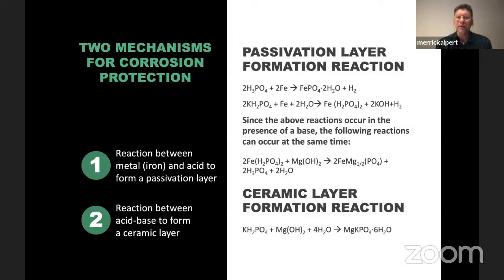And then second, what you're going to see as you're spraying it is the formation of that acid-base ceramic layer. Again, this is all going to look like you're spraying white paint. But if you slow down the reaction and think about what's happening, you are actually passivating the steel and you're forming an outer ceramic layer over the passivation layer. So again, Eoncoat is not a paint. It is a method for passivating carbon steel.